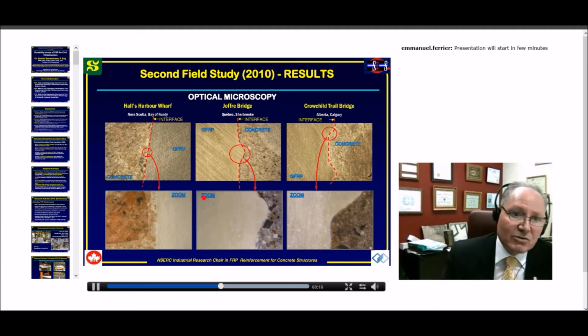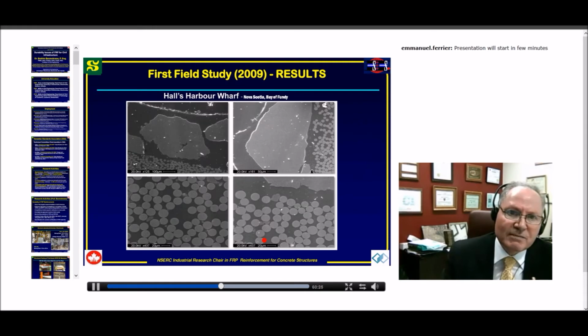So also we looked at the interface, as you can see here, and there is no degradation. It's almost the same result as in 2004. This is from SEM analysis, as you can see here, the fibers and also the resin.